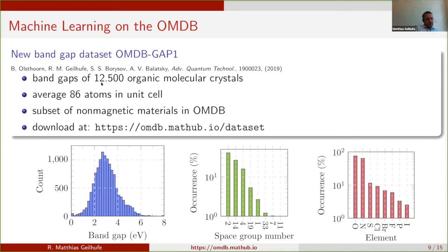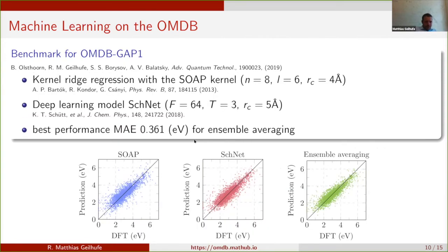The tricky part of this data set is that the materials themselves are typically highly complex. On average, our materials in this database have 86 atoms in the unit cell. That makes it quite demanding to cover this space, because you have variation in the number of atoms and variation in the local frameworks. And one big problem that I see is that pretty much all the methods that I'm aware of which exist to map the crystal structure into a descriptor for the machine learning model are focusing on local properties, right?